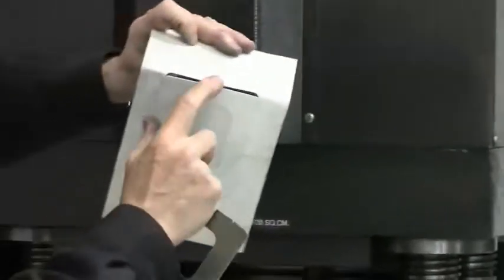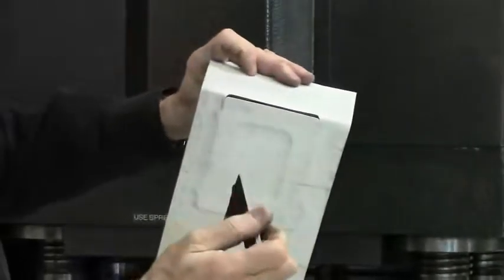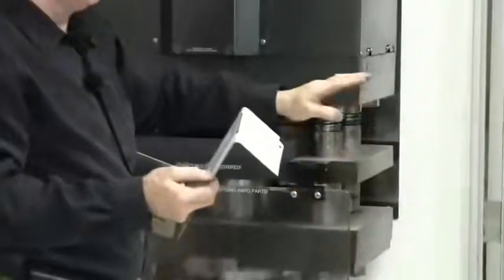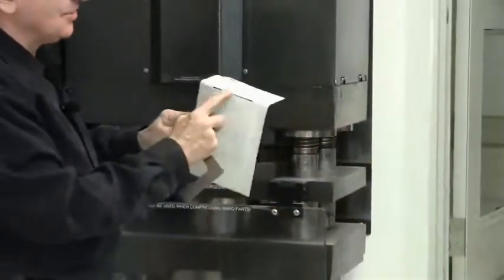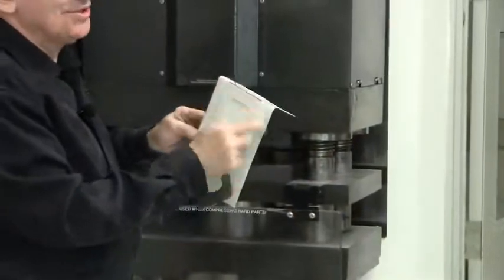But you also notice something interesting, because I didn't round the edges. It was on the borderline between pressing and shearing, and you can see at one end it sheared. See, if you look at this end, it actually sheared because one end was sharper than others. All the other tooling here have a rounded edge. So you can see you can use it as a very nice precise shear if this was hardened.